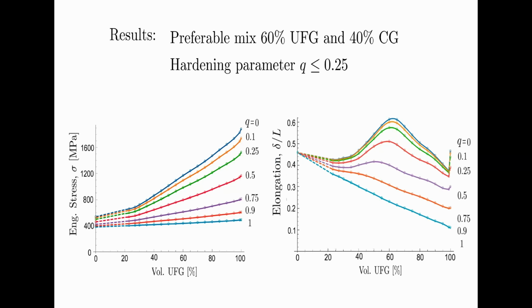So for around 60% ultrafine grain and 40% coarse grain got the best results. And then you see there is a jump at the end. There is also, for the stresses, a jump at this end also.